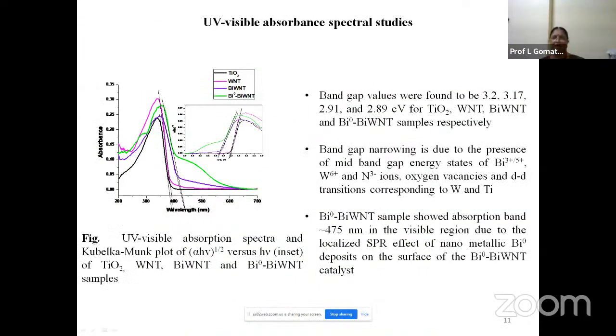Next, we have taken the UV absorption spectra, which is shown here in this figure, and the band gaps were calculated from the Kubelka-Munk method. The band gaps of all these catalysts we have prepared are 3.2 for TiO2, 3.17 for WNT, 2.91 for BiWNT, and 2.89 for Bi0 BiWNT. The band gap narrowing takes place for WNT, that is tungsten and nitrogen doped TiO2, because of these dopant ions. And in the case of BiWNT, that is also because of incorporation of the bismuth ion.